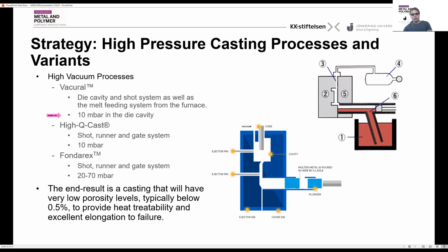The HiQ cast is one system. You empty the shot sleeve, the runner, and the gate system. It may also reach 10 millibar. Another process is the Fondarex process. This is quite common in Sweden actually, and you can also empty the whole system. This has a little bit higher end pressures than what you would have with the HiQ and the Vacural process. But what you will do in these processes, you will reach the 0.5%, which is the criteria for a high integrity casting. So we can go to the next.